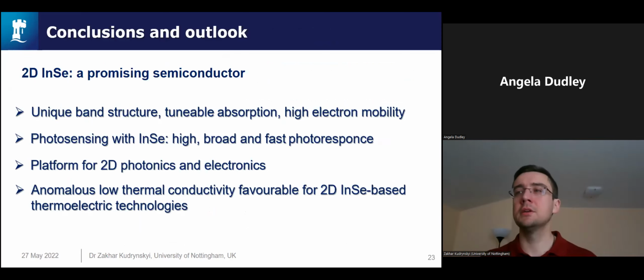I hope I've convinced you that indium selenide is an interesting semiconductor system, thanks to its unique band structure, tunable absorption, and high electron mobility. We successfully exploit these properties of indium selenide in a range of functional devices, in particular photodetectors, with high, broad, and fast photoresponse. The results suggest that this system could be a good platform for applications in photonics and electronics. In addition, anomalous low thermal conductance is favorable for 2D indium selenide-based thermoelectrical technologies.